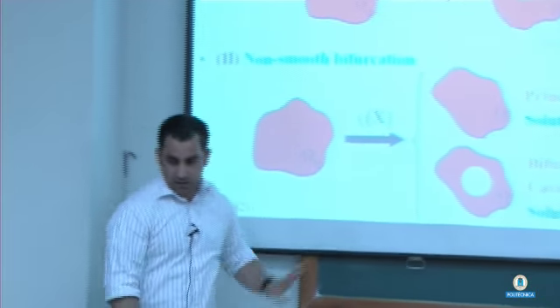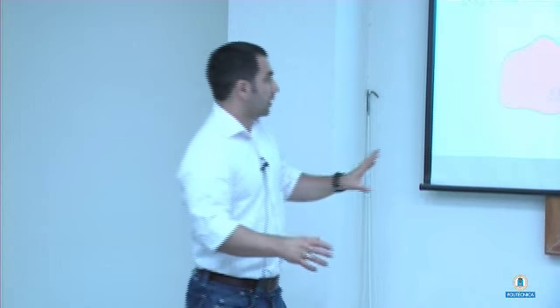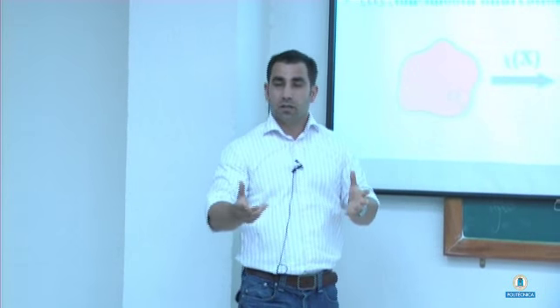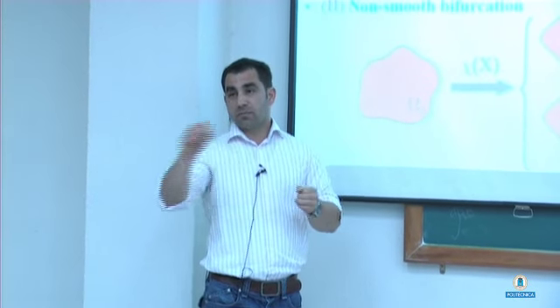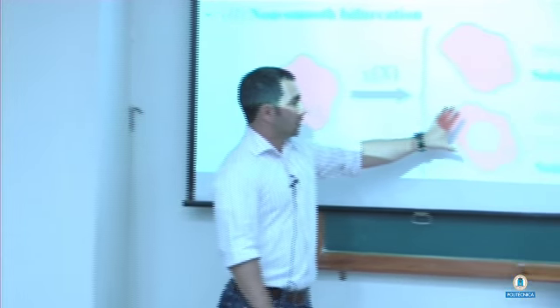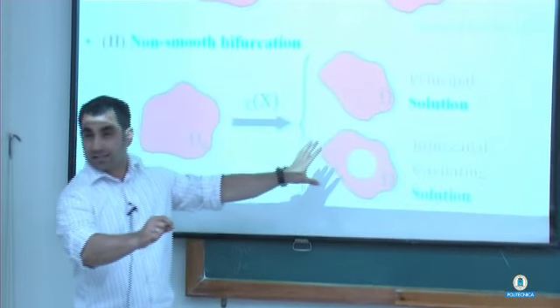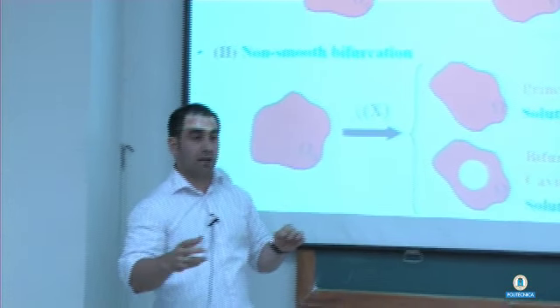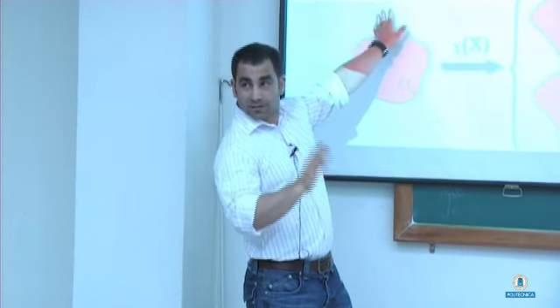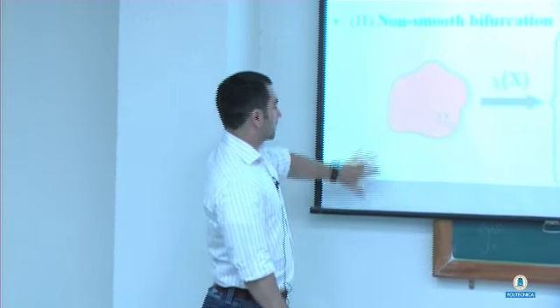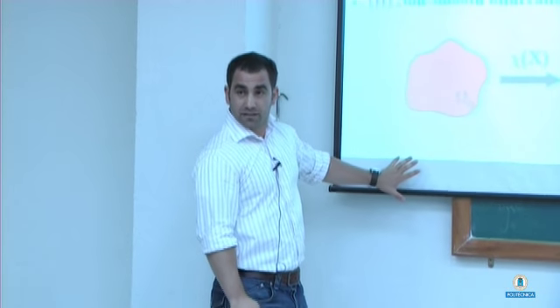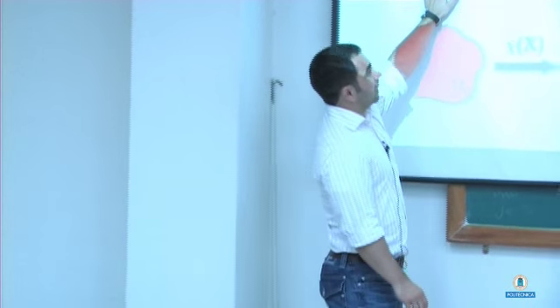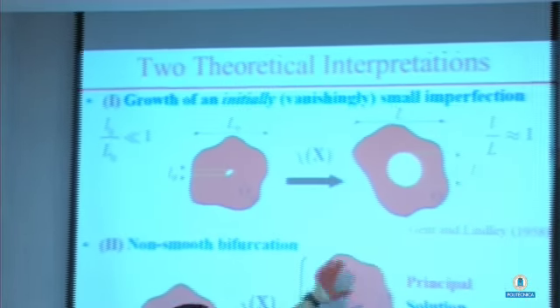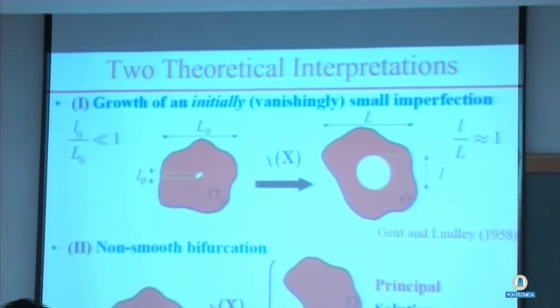And now, this bifurcation is challenging because, in general, when you deal with materials undergoing large deformations, or a continuum really, you enforce, in general, that the displacement field is continuous. Now, with this bifurcation, you have to allow the displacement field not to be continuous, at least at some point, so that the material can break, and then you can have cavitation. So that's why it's non-smooth. And then the non-smoothness is a very tricky one, right? So this proposal was put forward by John Ball in a famous paper of 1982, thinking of cavitation in this way. And this slightly less general proposal was put forward by Gent and Lindley in the paper that I show you with experiments.